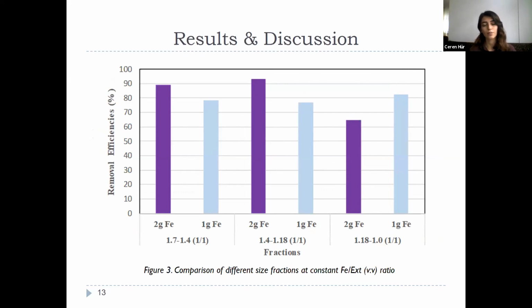It can be related with bentonite pore size. All fractions are assumed to have the same pore size, so their removal efficiencies are close. In terms of iron mass comparison, we achieved higher phosphate removal with 2 gram iron mass at constant iron per extract volumetric ratio. It may indicate that nanoparticle synthesis efficiency is dependent on the iron mass when the reducing agent is at a proper ratio.